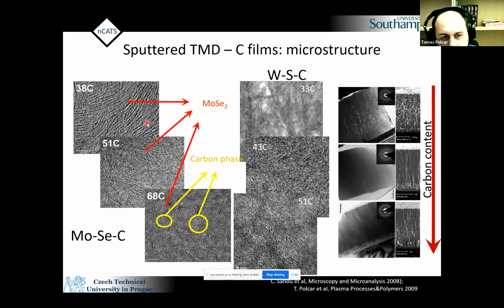These are cross sections from transmission microscopy of sputtered films, which contain molybdenum disulfide, or in this case, for example, molybdenum diselenide or tungsten disulfide, which are all very similar materials with similar structure and sliding properties. What you can see here is that if you sputter them as a thick film and you look into detail, you see that sometimes you produce these 2D materials. They grow basically during the deposition of the coating, which we still don't understand how it happens, but it's quite interesting. So you have a carbon matrix, for example. Here you have 68 atomic percent of carbon, which is the matrix, and inside you are able to grow, by this very complicated process that sputtering is, these 2D materials. And this is the coating which we produce, about 1 micron thick, and then we can use it in tribology.